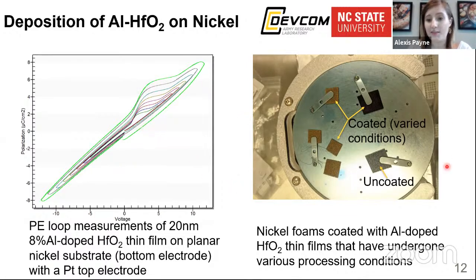And we've also started depositions onto the metal foams themselves. Here you can see an uncoated sample, which is very silvery. And then you can see all these have gone through at least an ALD growth run, and you can see that from their color change from the uncoated. They just have gone through various processing conditions. So we haven't gotten a polarization electric field loop yet off of a metal foam itself that's been coated, but that's due to COVID. Thank you, COVID. We're still really excited about this though.